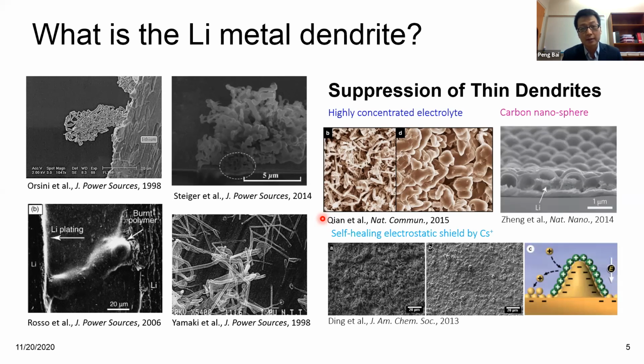First approach is basically to change the concentration or change the salt type of the electrolyte. By doing so, you can see that initially you will have fine structures, but by changing the concentration, changing the salt, you will get nodule-like structures that are more smooth. And the second type is to make an artificial interface, an artificial layer. For example, this layer of semi-sphere carbons. And this continuous layer can contain this kind of hazardous growth.